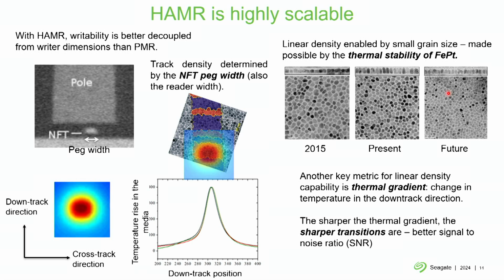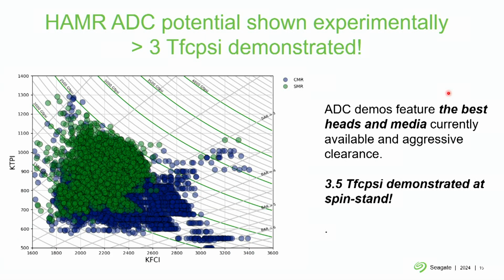So yes, HAMR enables much higher areal density than previous technology, and now we're just trying to figure out what else do we need to keep scaling the areal density with HAMR before we need to move on to some much more advanced technology. And one activity that we do in our group are areal density demos. So all of this data is produced by a test platform called a spin stand, which is basically like a large drive. And you can swap heads and media very easily, very quickly. So you can test out very experimental heads and combine the ones that give you the best performance.